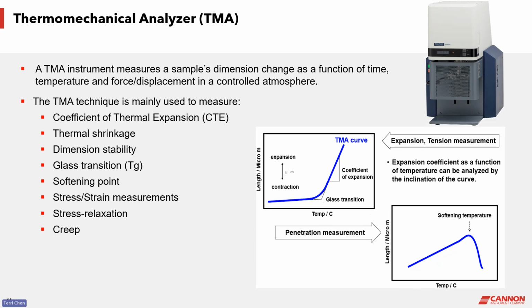The third thermal analysis technique I would like to introduce here is thermomechanical analysis. A TMA instrument is mainly used to measure a sample's dimensional stability as a function of time, temperature, humidity, or under a certain force or displacement. TMA is commonly used to measure a sample's coefficient of thermal expansion, the CTE. It can also measure thermal shrinkage, softening point, and glass transition temperature. A TMA is also capable of performing some basic DMA mode testing, such as dynamic temperature ramp, stress relaxation, or creep.